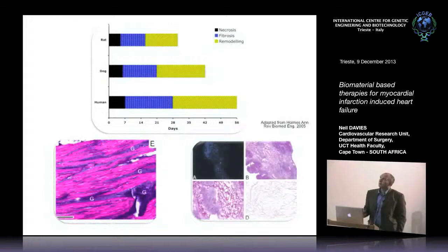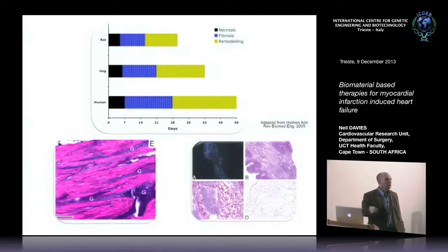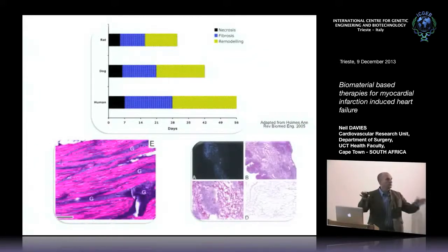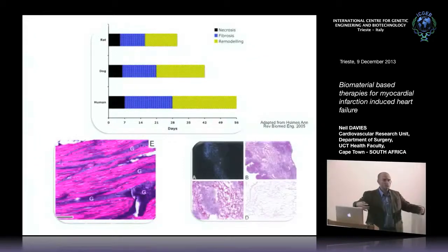These are exactly the same gels. The larger surface-to-volume ratio from the streaked pattern allows more cellular attack, so they degrade more rapidly. The inflammation explanation is unlikely, as there's still a very strong inflammatory response at one week in the rat. The patterning difference is probably because at about seven days, all cardiomyocytes have died and you're left with a bag of fluid with macrophages. When you inject immediately, you push it between cardiomyocyte bundles, giving streaks. After one week, you inject into a fluid cavity, giving a bulk blob.